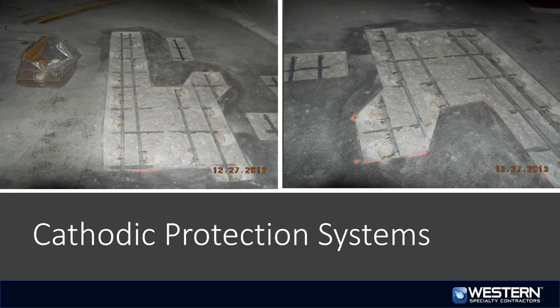Well, by putting in these zinc anodes, the zinc is a sacrificial lamb, so to speak, in that the zinc is what's going to corrode and not the reinforcing steel. And as the zinc corrodes, it is actually designed to where it basically sort of implodes rather than expands like steel does. When steel corrodes, it can expand to about 8 to 9 times its original size. So as you can imagine, that exerts a lot of pressure on concrete, and it puts concrete in a state of tension. And concrete does not do well in tension.